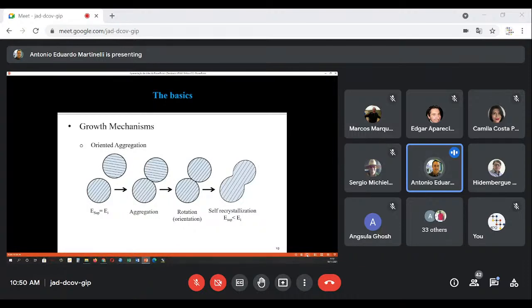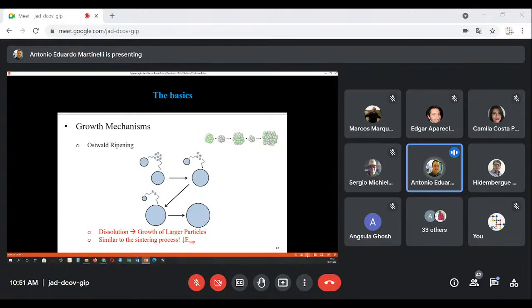Here we see the growth mechanisms. The growth occurs by oriented aggregation, which is shown here, when small particles with high surface energy aggregate in an oriented way, forming large particles to reduce their surface energy. The system also changes to a lower energy condition by dissolving smaller particles and anchoring the released ions on the surface of larger particles in a mechanism known as Ostwald ripening.